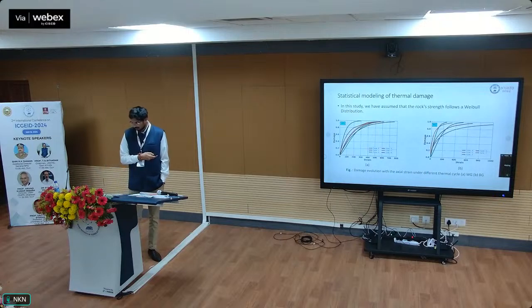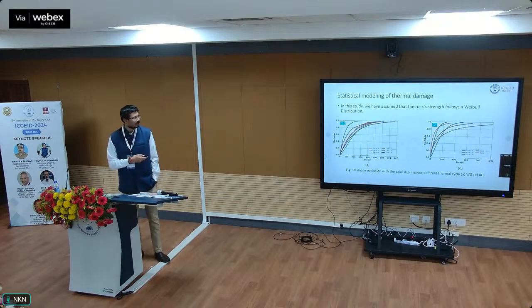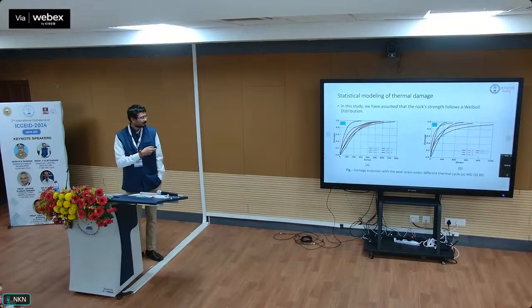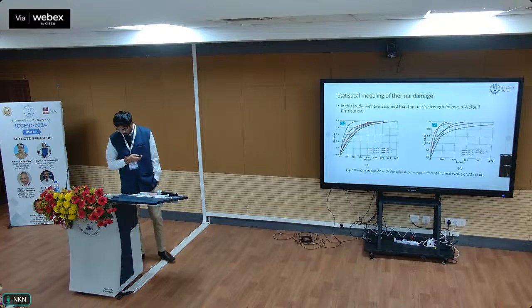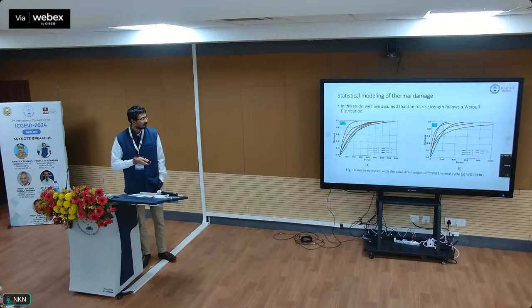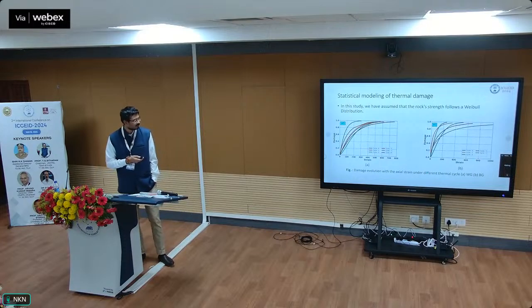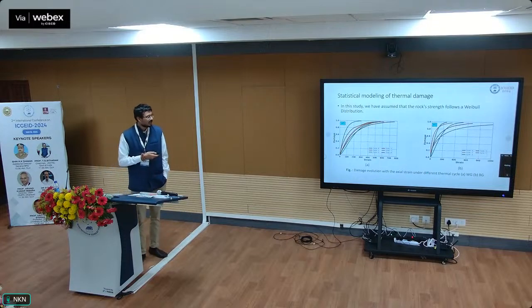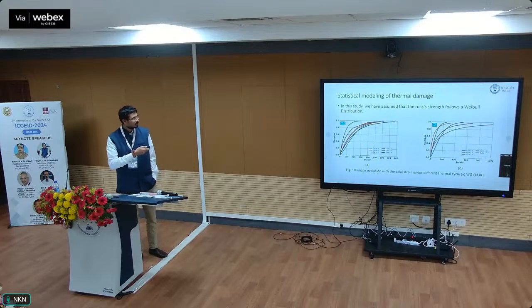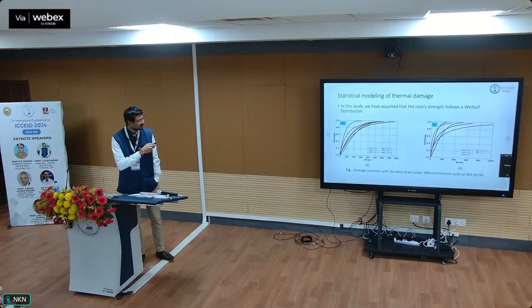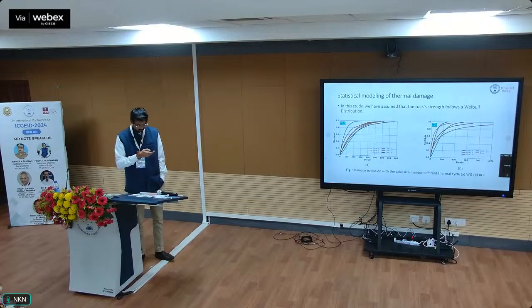After this, we have assumed that the rock strength follows a Weibull distribution, and we have plotted this damage versus strain graph, and we observed that the damage is basically what happened due to heating and cooling cycles. The microstructure within the rocks expands and shrinks. So there is thermal stress developed within the microstructure, and due to this, thermal cracks develop. So in white granite, because it is more stable, the thermal damages are not much distributed, but in black granite, it is showing a wide distribution.